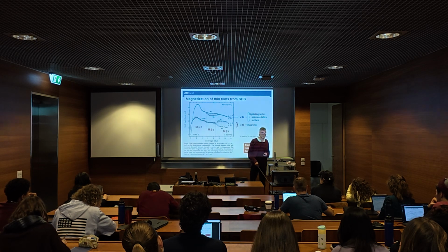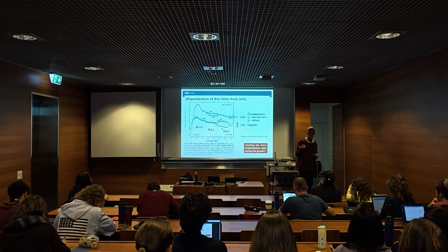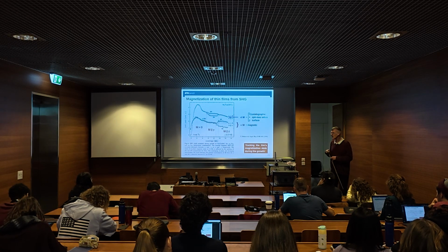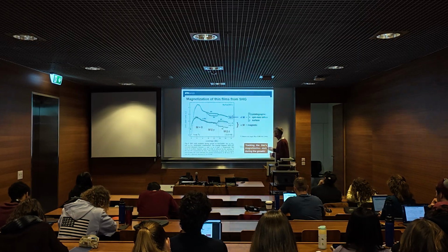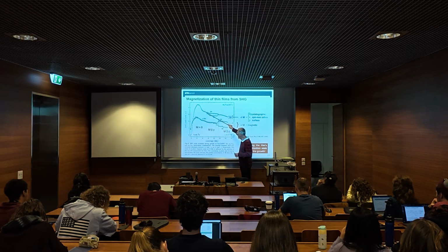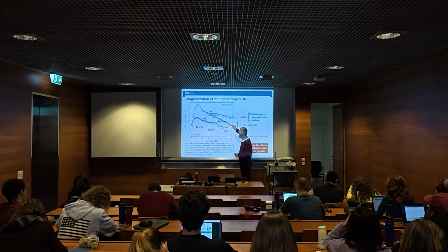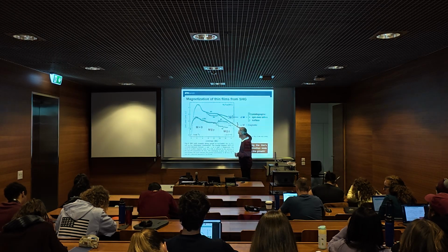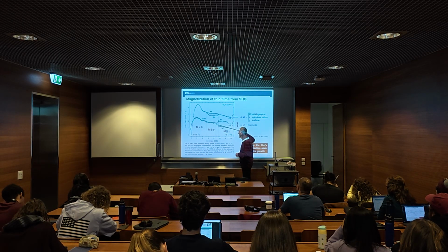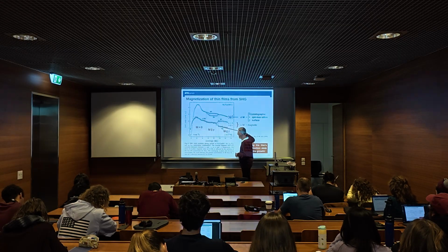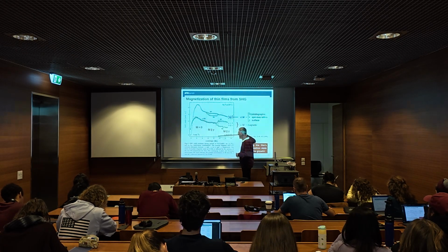That's a very important question when you work with thin films: when does the order actually happen? And here they see it while they grow. So here, at the 5th monolayer, it gets ferromagnetic. Then suddenly it's gone again, and now it shows up in a differently polarized contribution of your signal. So here the magnetization changes direction.